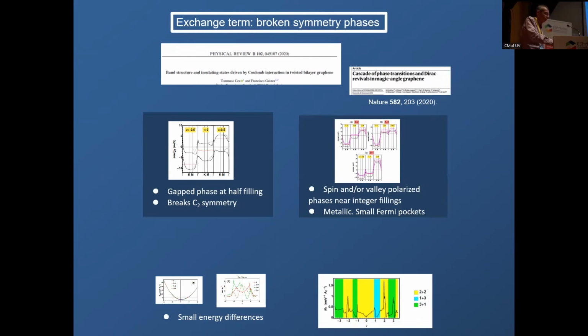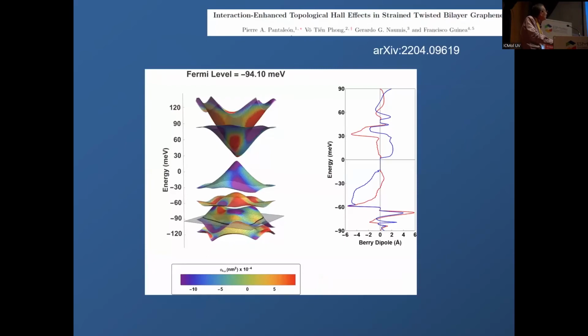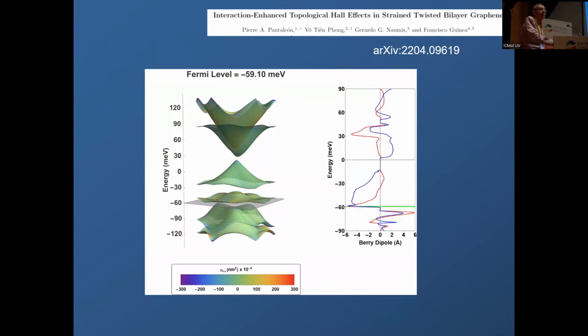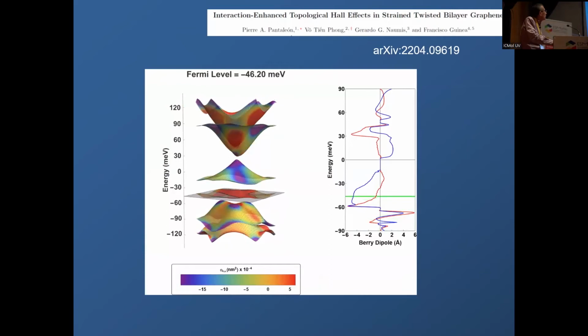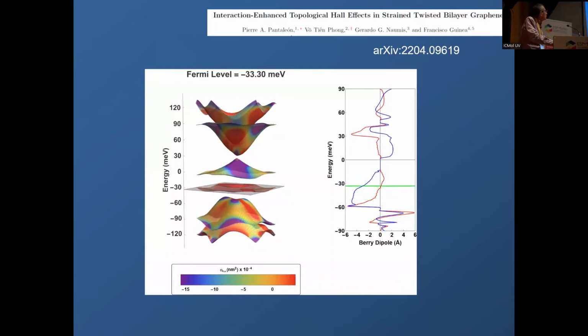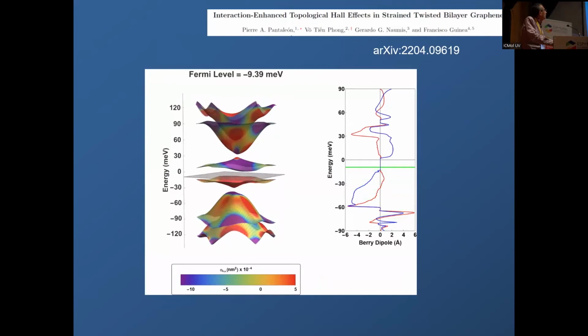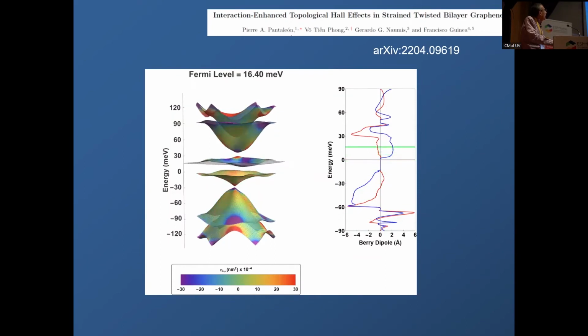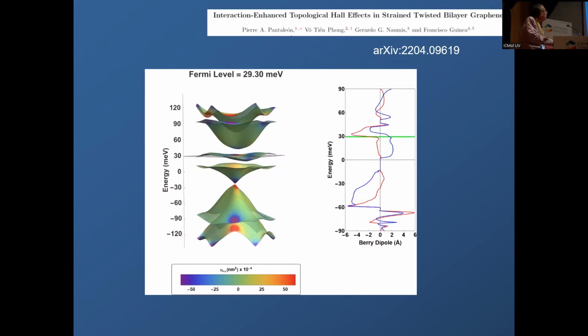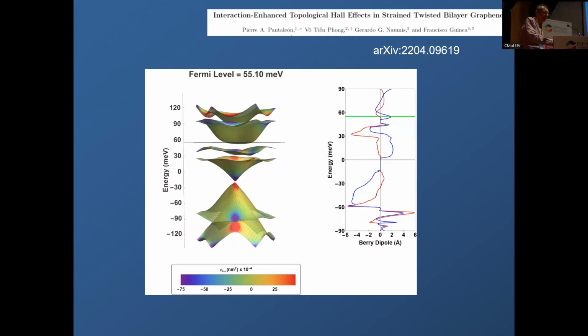These are our calculations. By the way, these are the bands in twisted bilayer graphene as a function of the Fermi energy. And you see, all of a sudden, when the central bands start to be filled, the bands change shape completely. That's what I mean. It's very unusual in a condensed matter system. And the Fermi level continues to grow and grow, goes to the second central band, which are the important ones. And you see that again, the whole spectrum is changing as you increase the Fermi level. And then eventually the chemical potential moves into a higher band and things stop. The bands behave rigidly, which is what you find in most systems.